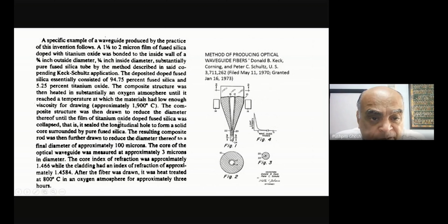The composite structure was then drawn to reduce the diameter thereof until the film of titanium oxide doped fused silica was collapsed. That is, it sealed the longitudinal hole to form a solid core surrounded by pure fused silica. The resulting composite rod was then further drawn to reduce the diameter thereof to a final diameter of approximately 100 microns. So you can see that we are starting with something like a 3/4 inch tube, and when I have made the fiber, it is achieving an overall outer dimension, OD, of about 100 microns.